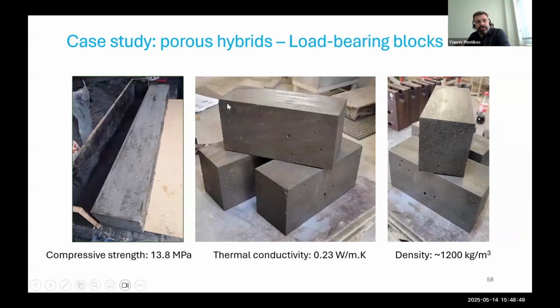This is another story here. We bring now porosity, and here is a compromise between introducing porosity in the material, but not losing sight from the mechanical strength. So the compressive strength is about 14 megapascal. You see here thermal conductivity and the density. And again, we start with a slag that has initial density 3.5 to 3.6 grams per cubic centimeter. So it is a difficult slag, quite heavy to have low density. But we have a process where we introduce this porosity.